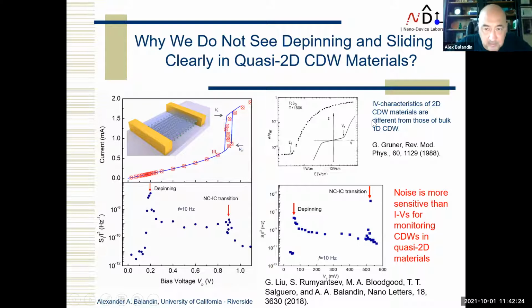So if you look at this picture from George Gruner's review, you see a threshold. There is a strong increase, right? And we don't see it. Well, we have a slight increase. Initially, we thought that maybe when you have this onset of superlinearity, this is the onset of charge density wave. But so far our functionality was based on just this hysteresis, the phase transition between commensurate and incommensurate.